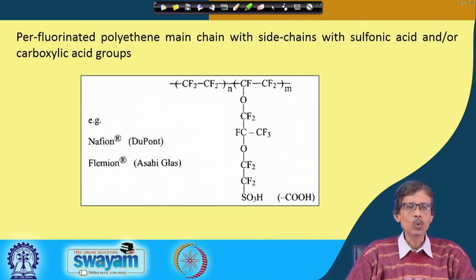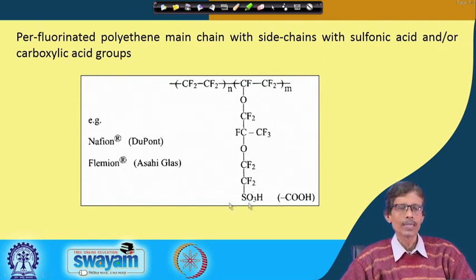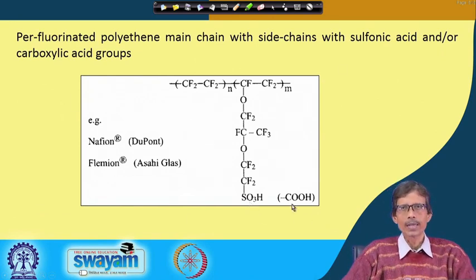So, by two names basically, because simultaneously two competitor companies can do the development of this particular material. The other one is Flemion, the name is different, but the material is the same. But if we consider that first people have identified the sulfonic acid functionality, the second people can use a carboxylate functionality, only a little bit different in their corresponding activity or effectiveness for that particular purpose.